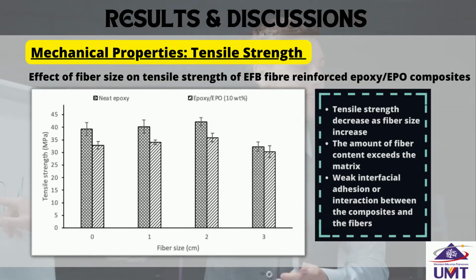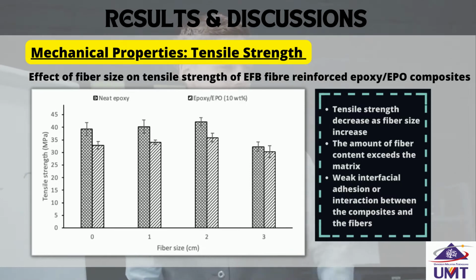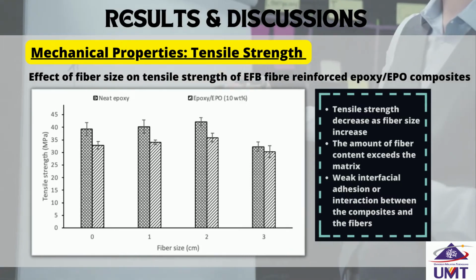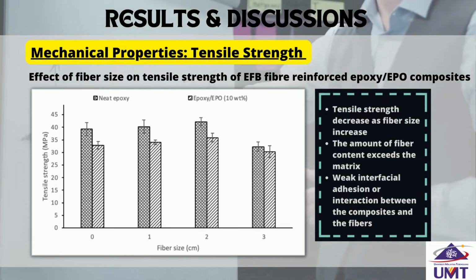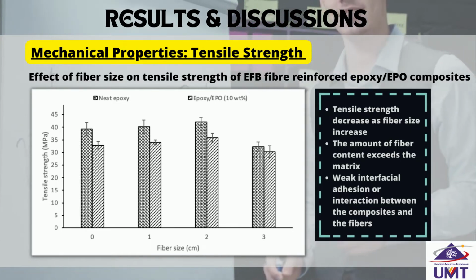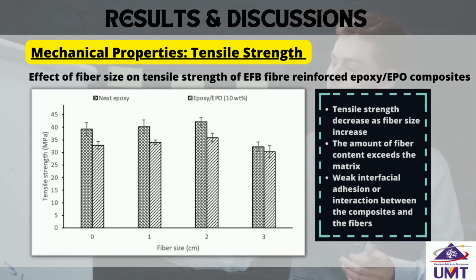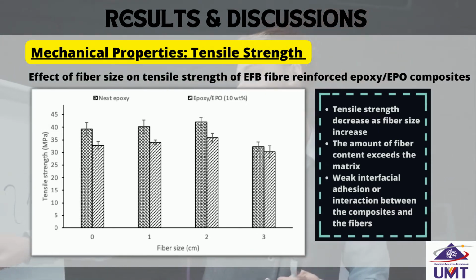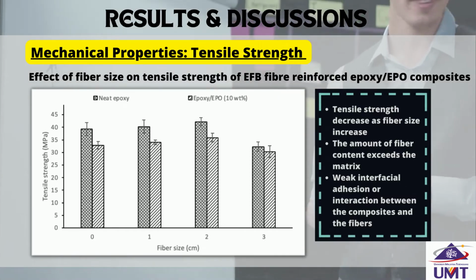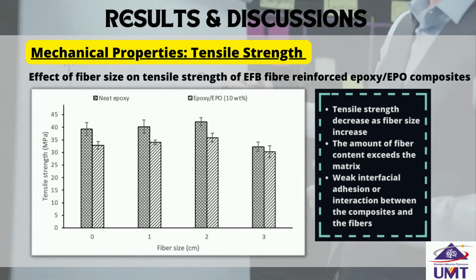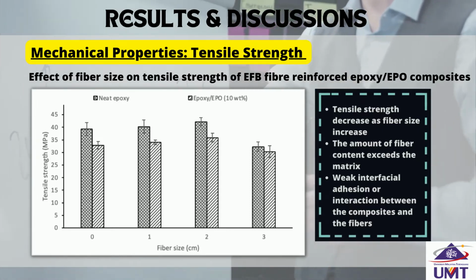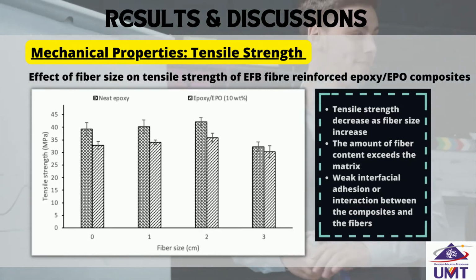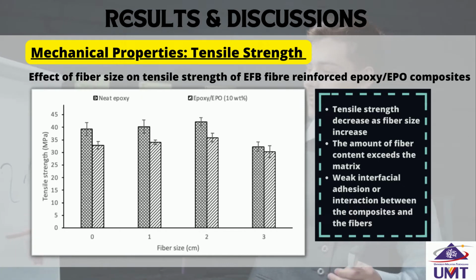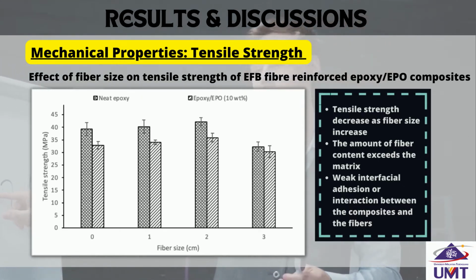Ramli 2011 stated that the decreased result in tensile strength occurred due to the weak interfacial adhesion or interaction between the composite matrices and the EFB fibers. Moreover, irregularly shaped fibers such as EFB fiber with shorter fiber length employed in the study may not be able to withstand stresses imparted from the polymer matrix, resulting in a decrease in tensile strength as the fiber size was increased. Next, clearly between neat epoxy and epoxy EPO composite there is quite a different gap. In the presence of a high amount of EPO, weak spots may exist at the end of the free chain for the nucleate voids.